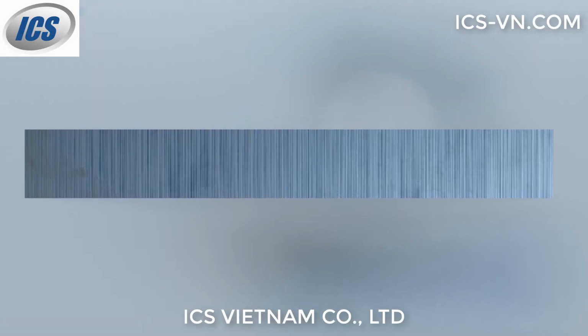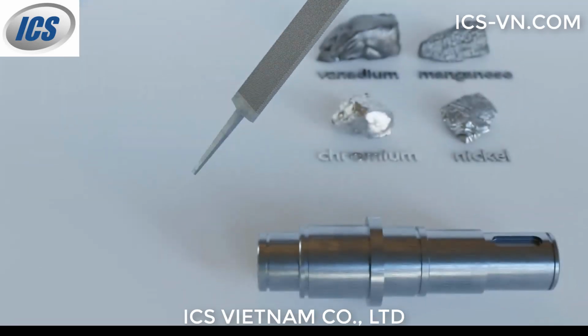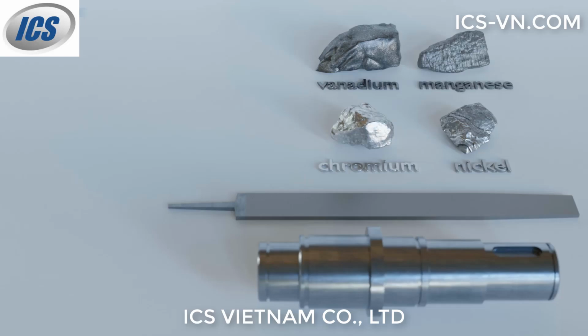Even higher cooling rates to achieve complete hardening have their limits. Extreme cooling rates can lead to high thermal stresses in the component, resulting in so-called quench distortion or even cracking.